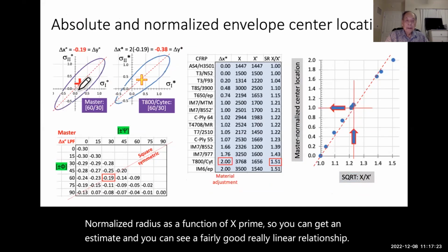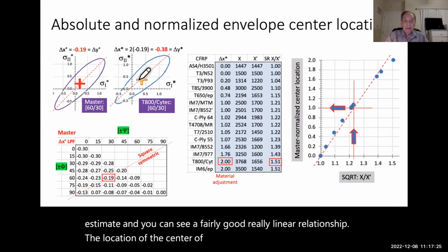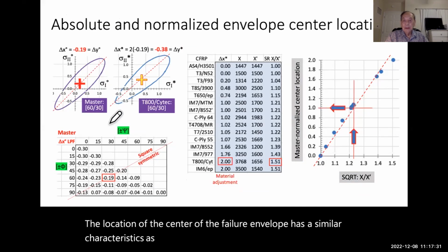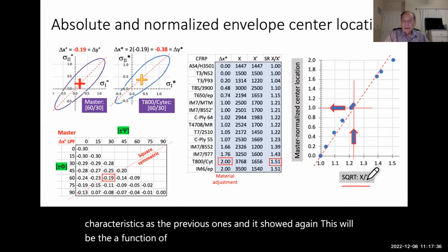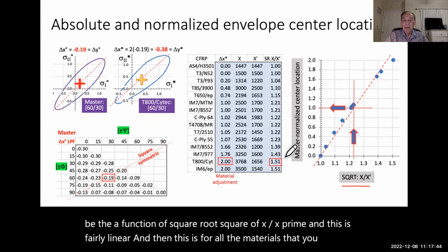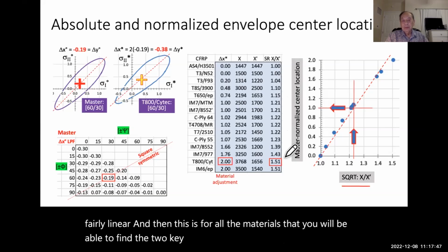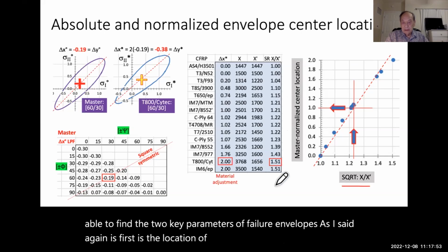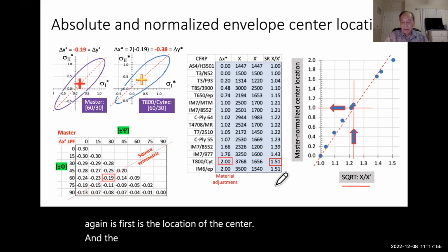And the location of the center of the failure envelope has similar characteristics as the previous ones. It shows again, this will be a function of square root of x over x prime, and it's fairly linear. This is for all the materials, and you will be able to find the two key parameters of failure envelopes, as I said: first is the location of the center, and then the dimension, the value of the radius, the average radius of the envelope.